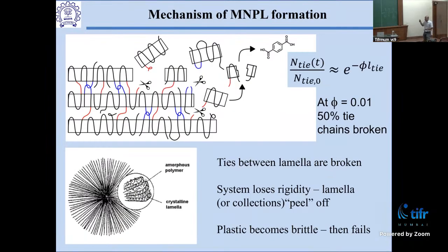Okay, and so this is really the mechanism that we see, is that if you take these polymers that can crystallize, the crystals form these sheet-like structures. These are tens of nanometers in size. They're connected by these tie chains. And over time, if you expose it to, say, free radical attack or oxidation, it starts breaking these tie chains, and that gives rise to these particles, and these particles persist in the environment, and these are pretty much impossible to degrade over any reasonable period of time. So that's the first part of my story.